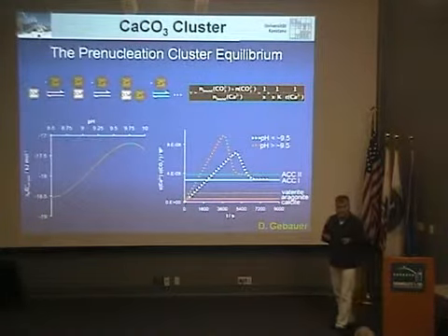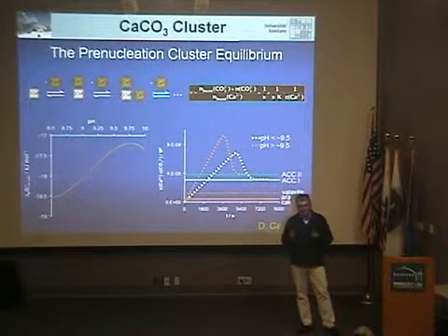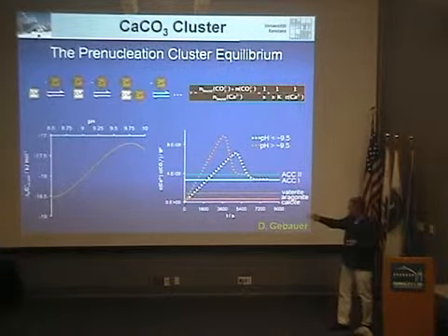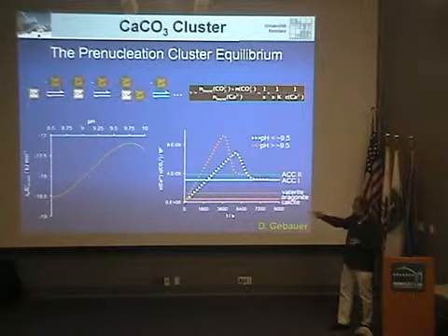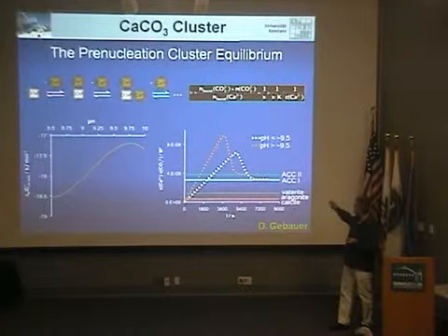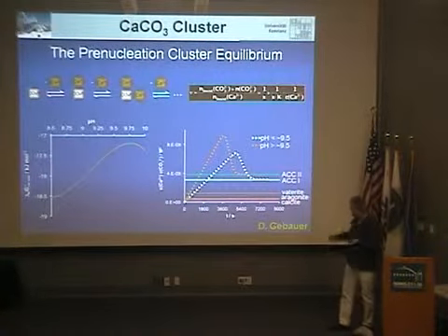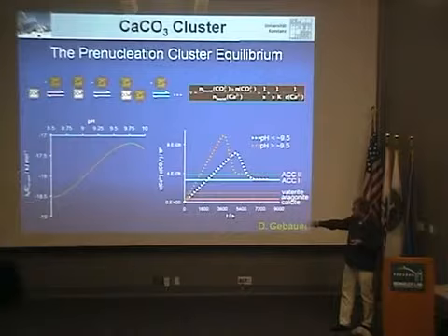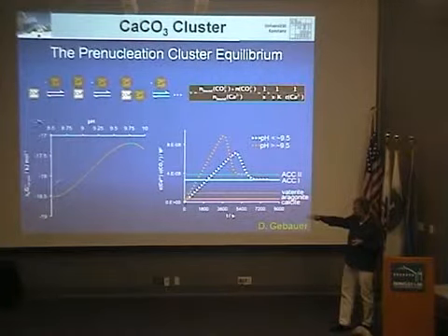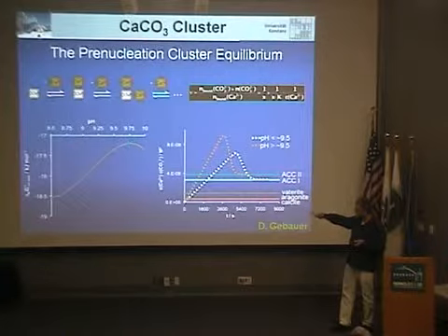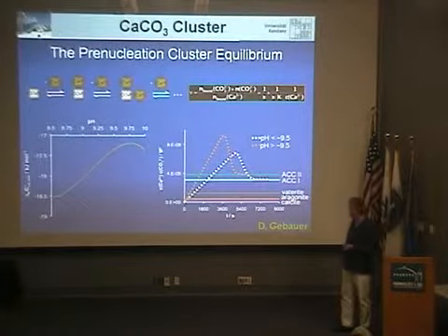And it's very interesting that these clusters already seem to have different structures. So if you look at different pHs, you can describe these clusters by a binding equilibrium here, and this is a formula for it. And from that, you can get an equilibrium constant for ion pairing and cluster formation. And if you do that, you can plot the free enthalpy of ion pair formation versus pH. And you see at a lower pH, I have the most stable clusters, and these guys finally end up in calcite, whereas at a pH of 9.75, I get a situation which is less stable, and they form vaterite.